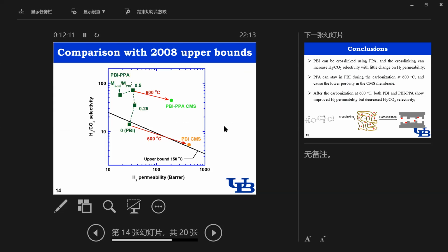Then we compare those performances with the upper bound, and we found that, firstly, for acid doping, we can increase the hydrogen CO2 selectivity with a little loss of hydrogen permeability, and then we carbonized the best doped PBI and get high hydrogen permeability, with some loss in hydrogen CO2 selectivity.